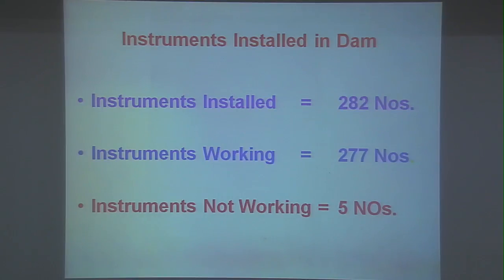This was only possible because we had a separate contractor for this. And at the time of installation, our engineer in charge, who is sitting here, Mr. Vinod Verma, I was in charge of the instrumentation, and a person from the contractor side, we used to be there. If you install the instrument, put the first layer, and cover all the instruments with the first layer of concrete, then you should not worry about it. We should take care of the instrumentation. Only 5 instruments were not in working order. One had some fault with the instrument, and 4 instruments were not working because of a water leakage problem.